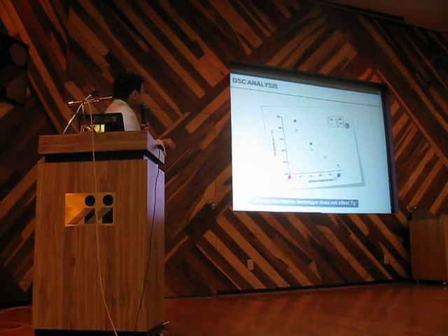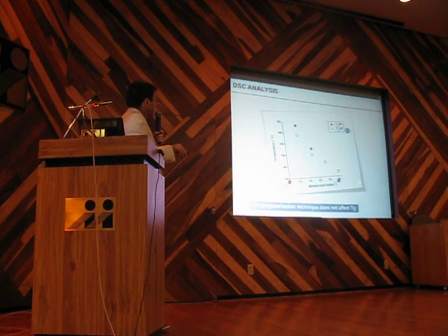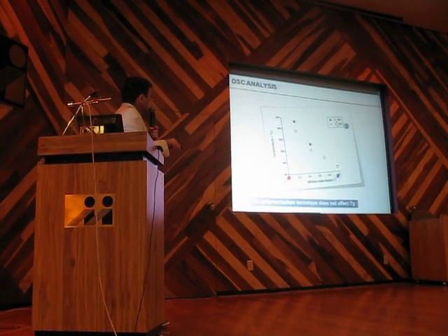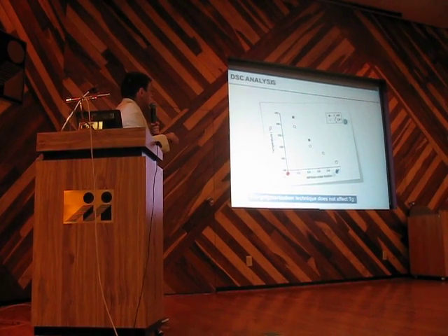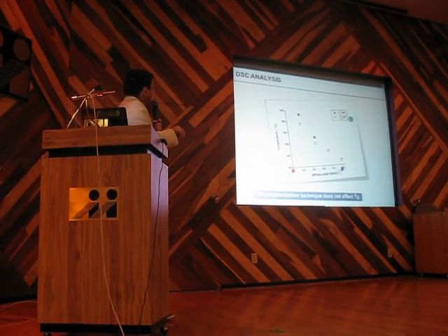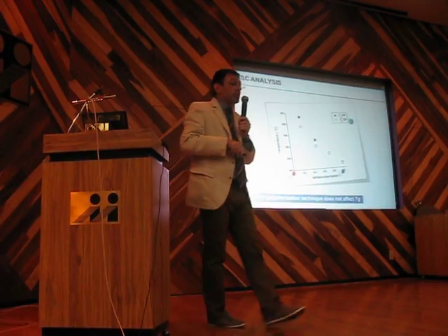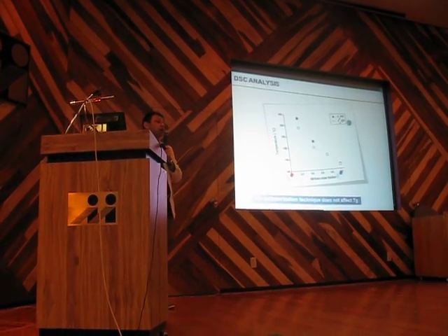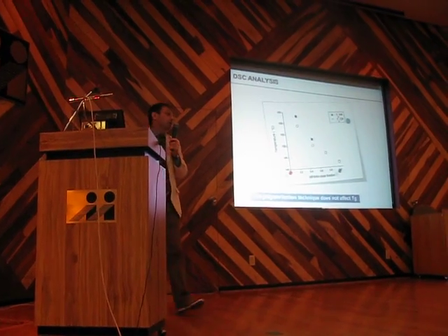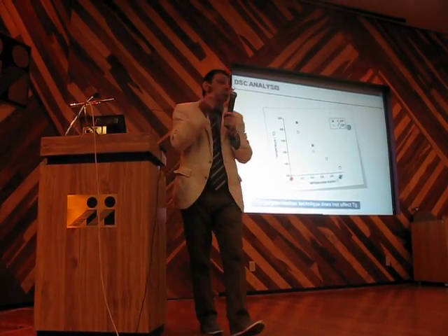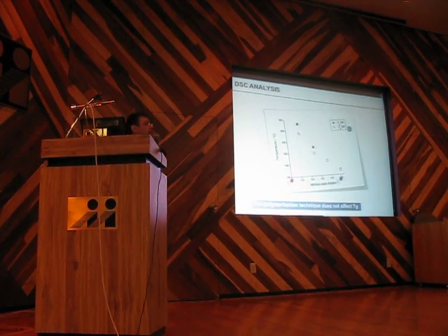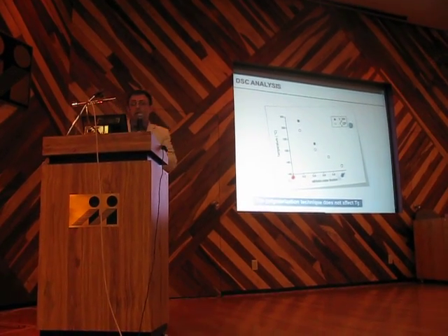If I compare the samples obtained by the classical polymerization and the frontal polymerization, we don't observe almost any difference in the glass transition temperature, but I remind you that frontal polymerization happened in 5 minutes, and the classical polymerization took about 2 hours.